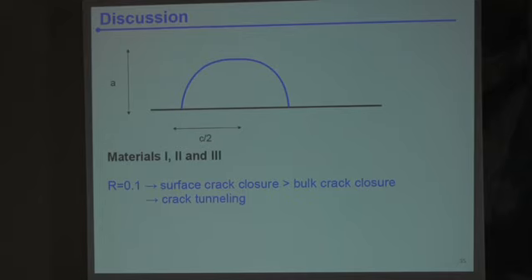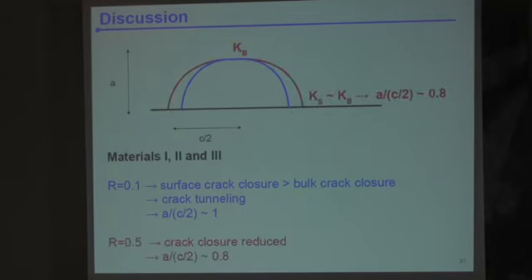So if now I'm discussing what we get, for materials 1, 2, and 3, for R equal to 0.1, we believe that we have some surface closure, which is larger than the bulk one, even if the samples are smaller, and that we do get some tunneling. It means that the crack fronts are held back by some closure here. And the result of that is that your crack aspect ratio is nearly 1. Now if you increase the load ratio, you release this crack closure on the surface, and your cracks start to grow with a 0.8 crack front ratio.